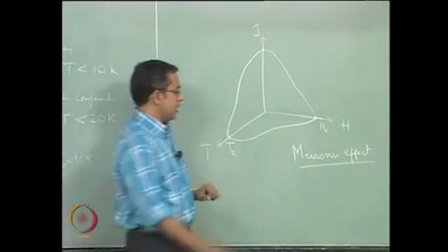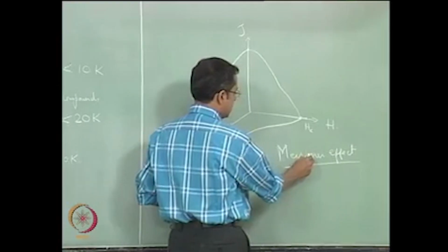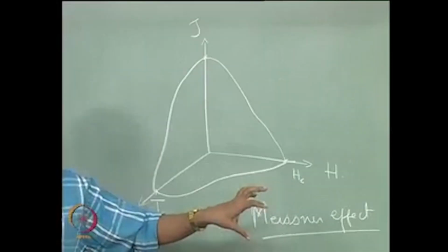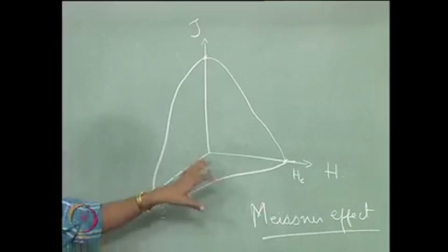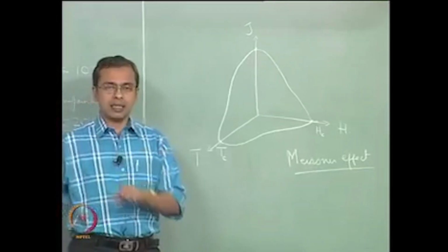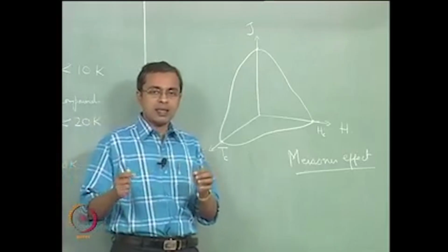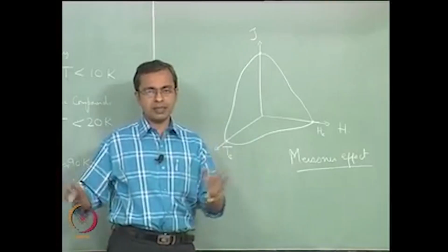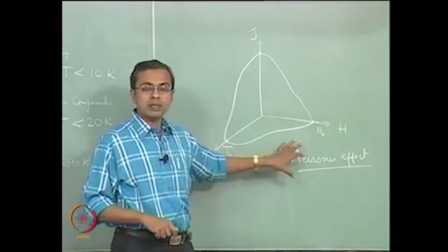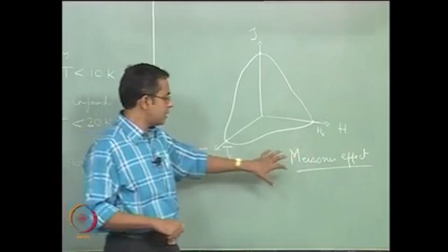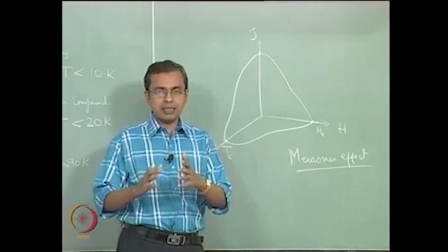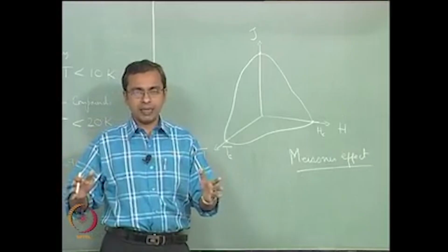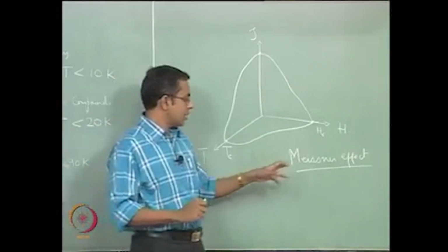Now this is considered a very important effect that was discovered about superconductors, because the fact that the Meissner effect exists indicates that a superconductor is not simply an exceptionally good conductor, okay. If you take a very good conductor, and hypothetically you find ways to reduce its resistance, it will still not display the Meissner effect. The Meissner effect ensures that no matter when or how the magnetic field is applied, the material will exclude that magnetic field. So it tells us two things.